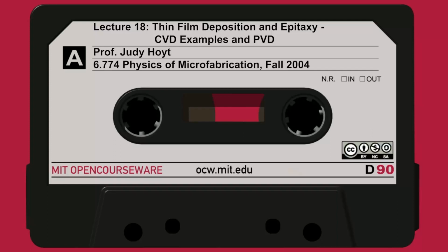Remember earlier in the course we talked about growing silicon dioxide. Well, now we're talking about depositing it, which is quite different. We typically react silane as a precursor with oxygen to form SiO2 so that you don't have to have silicon exposed on the wafer. You don't consume necessarily much silicon on the wafer. This is listed between 200 and 800. That's a pretty wide range. Really the most common is between 200 and 500.